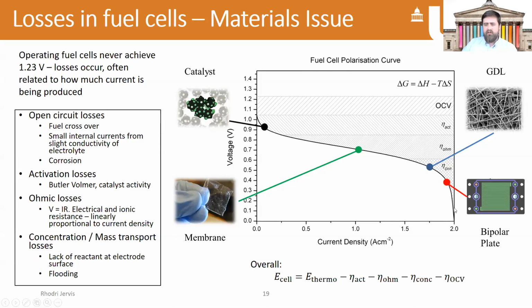As we get into higher current densities, we're driving these reactions even harder, and we're generating a lot more water, and we're also requiring a lot more reactant to get to the surface in order to satisfy the rate of reaction that we need to produce this kind of current. Okay, and so if we're unable to do that, then you actually start to get a drastic drop off in the voltage, and that could be due to flooding with water in the structure of these GDLs, and also the current collector bipolar plates. We could get droplets of water blocking the channels there, so we're not getting enough reactant at the electrode surface. So all of these properties need to be taken into account in order to minimize all of these losses and get a more efficient and better performing fuel cell. Okay, so lots of different material properties required to work in tandem there.